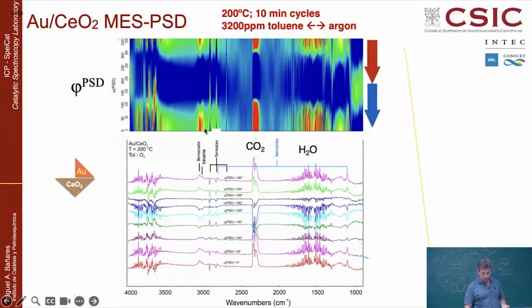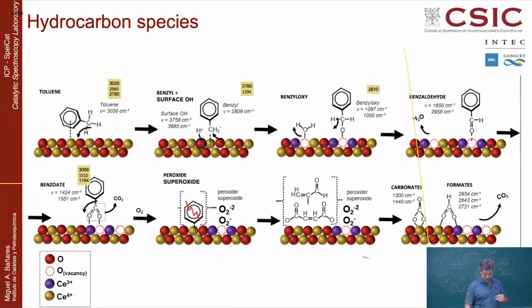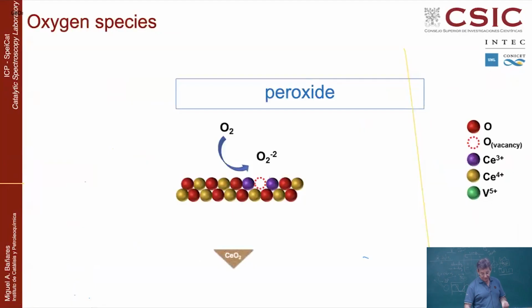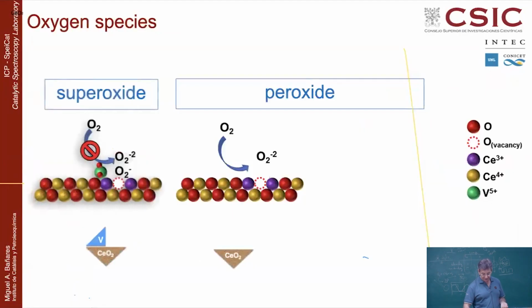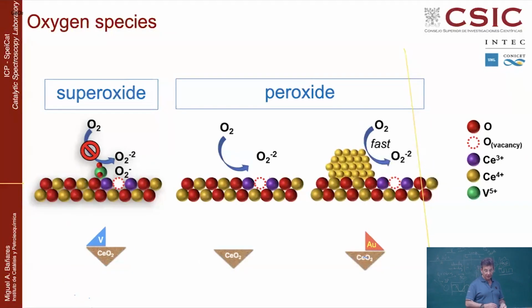And again, this is because you're doing the perturbation and because you are going into the phase domain. So then you can go into the reaction mechanism, you can see how the toluene is adsorbing, and basically get insight at the moment where the aromatic ring is being broken and ultimately decomposed into carbonates and formates, this kind of species which are being formed at this transition period. And this is the insight which is still under progress and under analysis on these systems. We're also doing a similar analysis with Raman, which is much more sensitive to the response to peroxide and superoxide species. And these are ongoing projects.